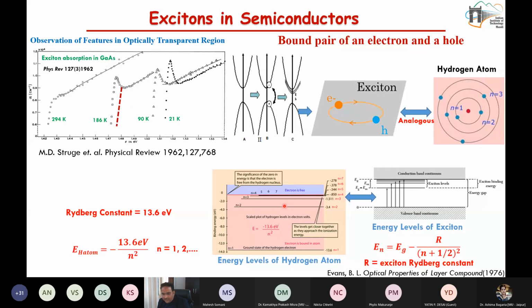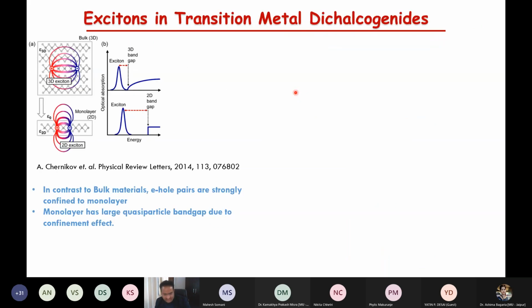So you have the energy levels associated with the excitonic levels, and you have the excited states of the excitons. Okay, they lie right below the bottom of the conduction band. So then you have multiple transitions coming out from this. Especially in the case of these transition metal dichalcogenides, if you have a bulk, then the excitons actually can move.